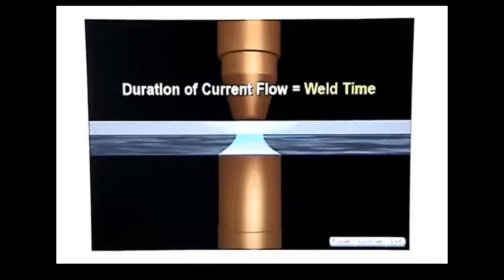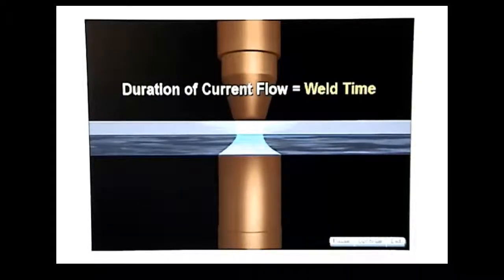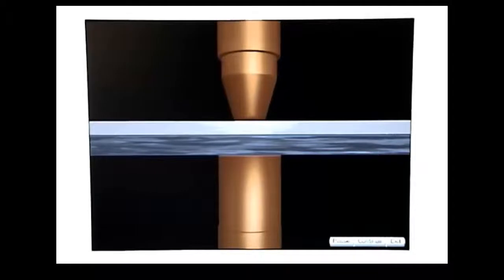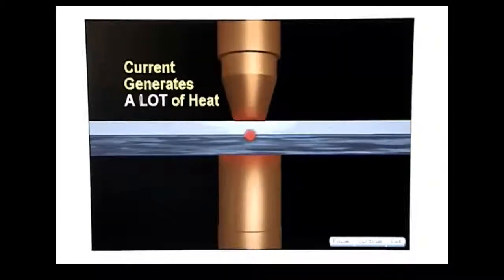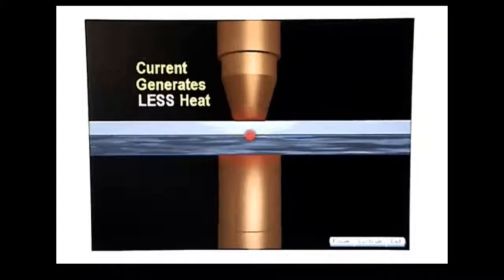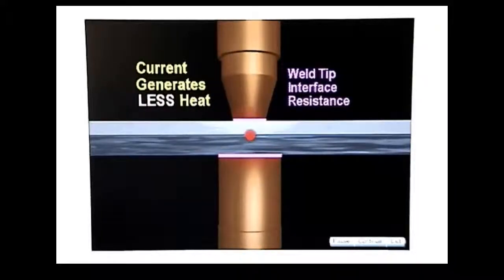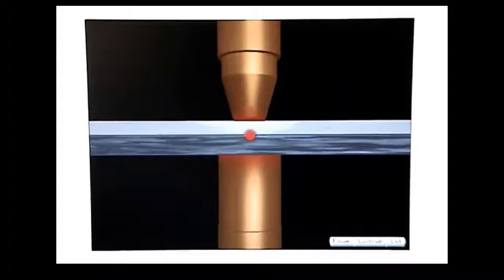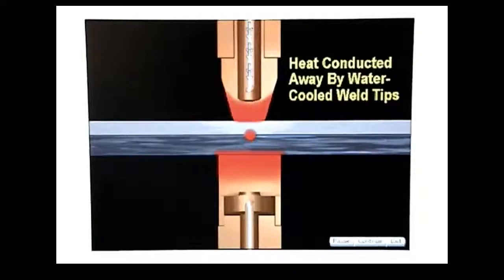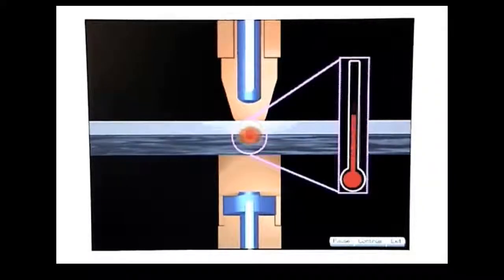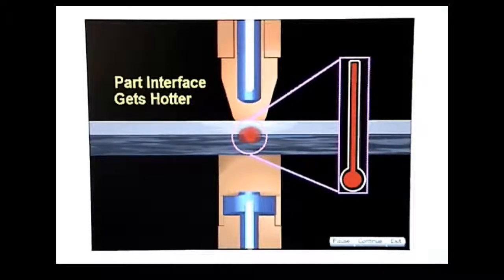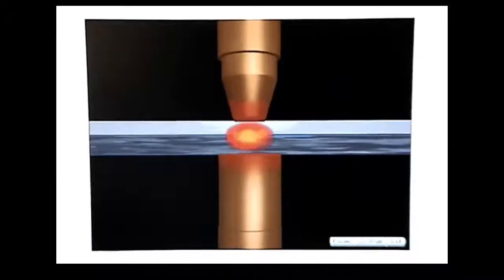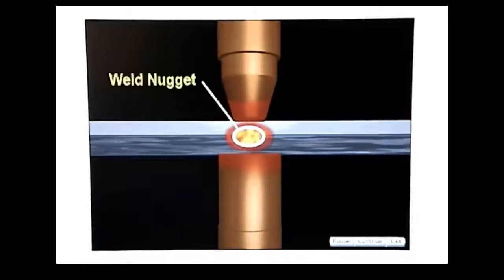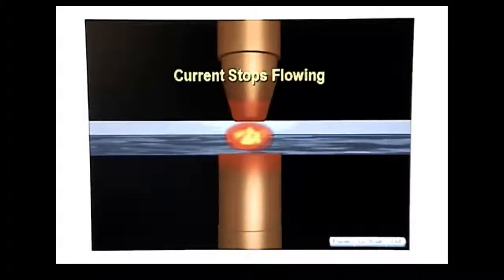The duration of the current flow is referred to as weld time. The current generates a lot of heat when it encounters the resistance at the part interface, and a lesser amount of heat at the weld tip interface. The heat at the weld tip interface is conducted away by the water-cooled weld tips, while the part interface continues to get hotter and hotter. About halfway through the weld time, the metal at the part interface begins to melt, then a weld nugget is formed. When the weld time is complete, the current stops flowing.